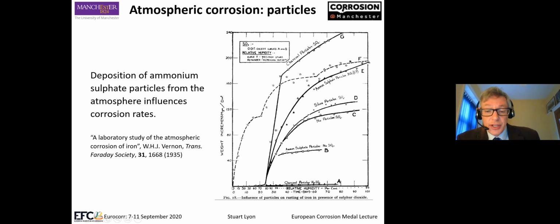And he's raising the humidity until corrosion kicks in. So this is the critical relative humidity for corrosion, around 75% or so. In the absence of SO2 contamination, we get quite low corrosion rates. In the presence of ammonium sulfate, we get a significant increase in corrosion rate. With no particles, we get this corrosion rate. Interestingly, with silica particles, inert particles, we still get an increase in corrosion rate, and that's due to the crevice corrosion or differential aeration effect underneath the particles.